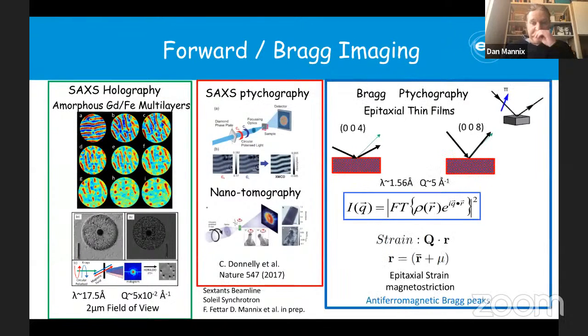But what I wanted to do is talk a little bit about contrasting some different methodologies. Imaging and coherent diffraction imaging has been around for a while, studying magnetic materials. This is something we've been doing recently at the Soleil synchrotron using SEXTANT, looking at the formation of skyrmions in a magnetic field in amorphous gadolinium multilayers. We use a technique called holography, essentially in a small angle scattering regime, where you interfere your coherent diffracted image with a reference hole.